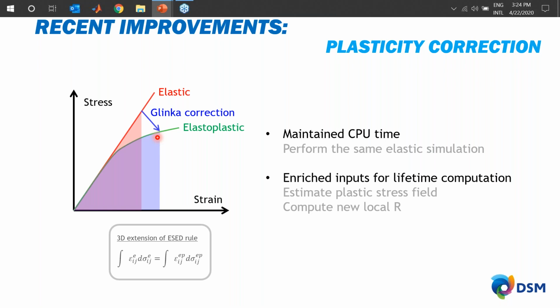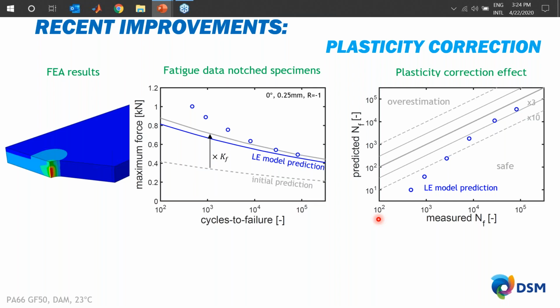And they can do it so efficiently that they have a hybrid option to do this only for, let's say, the elements that exceed a certain yield stress. And with those image inputs, we compute the plastic stress field and also compute the new local R. To give you a glance at this, I already demonstrated that we compute KF and underestimate the initial local stresses. And therefore, we also see deviations, let's say, at the lower cycles where you start to underestimate the performance.